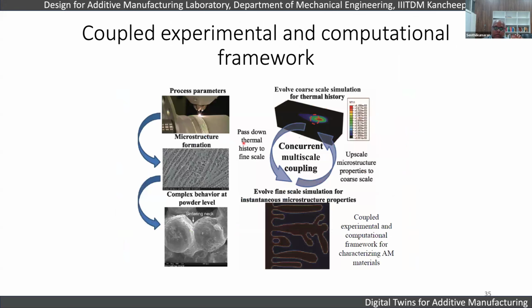So when you couple experimental work, so for example, when you have a microstructure formulation from process parameters, this is an example from DED, directed energy deposition, you can understand how the fine coupled experimental and computational framework can be used in concurrent multi-scale coupling. That means you are taking results from the macro scale and then using that results in the micro scale, and then again taking the data to the meso scale to basically again influence it in the macro scale.